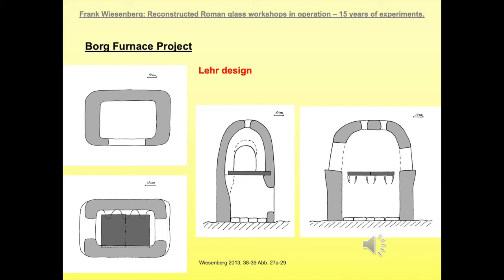a solid back wall and pretty solid side walls, which can be used as a support for some tile doors to close the vessel chamber of the annealing oven. There are 2 small chimney holes, which could be closed, but are left open during the working phases mainly. So the hot gases travel from the fire pit down below, this sort of separating Roman roof tiles, which serve as the floor or base of a vessel chamber.